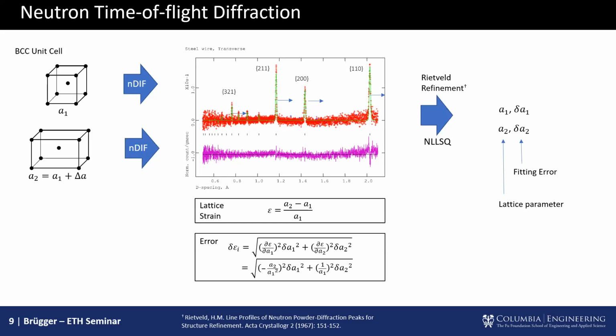It's a very good question, and this is, in any residual stress measurement, always the sort of art, science and the voodoo, right? Of where you start. What is your D0, your unstressed lattice parameter that you consider to be healthy or zero or whatever you want to call it? Here, normally what's done is you actually take a piece of your sample and then you cut with laser EDM, for example, laser or just EDM, electrical discharge machining, you cut a comb into the sample and then you measure that comb, and that comb is then stress-free, close to stress-free. So that's sort of the traditional by the book method.